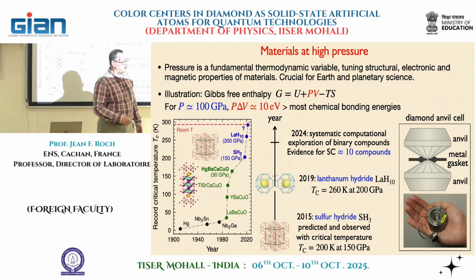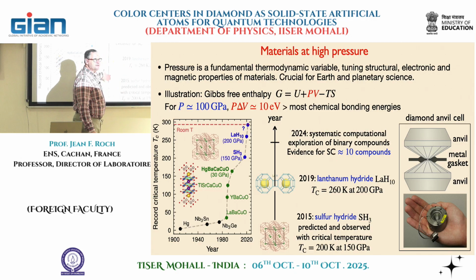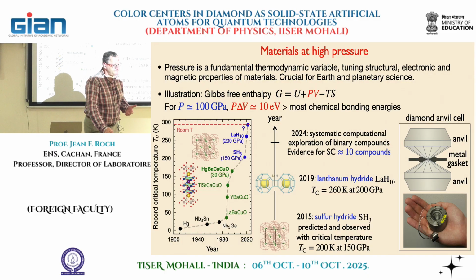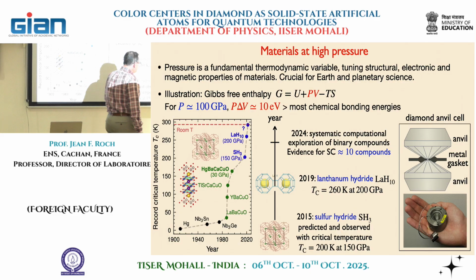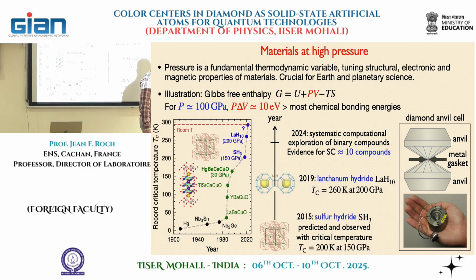I could go to a synchrotron, for instance, and do X-ray measurement to identify the structure of those materials, and actually this is what has been done. So it's a very practical tool. You can even control the pressure in situ by controlling the force that is applied on the outside of one of the anvil, and for that, we have here a membrane, and we insufflate gas in the membrane. And just due to the difference of surface here to here, we control like that the pressure inside the cell.